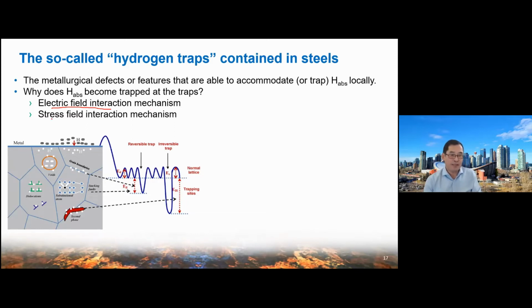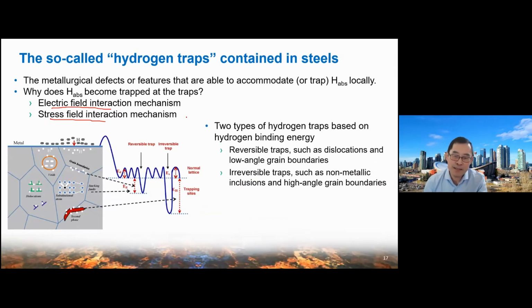The second mechanism is the stress field interaction. Local stress concentration can create a little more space to host hydrogen. Anyhow, these are the two basic mechanisms by which hydrogen can become trapped, depending on the trapping energy level. In the steel, there are two types of hydrogen traps. One we call reversible. Reversible means the trapped hydrogen can also leave these traps very easily. For example, dislocations or low angle grain boundaries are reversible traps.